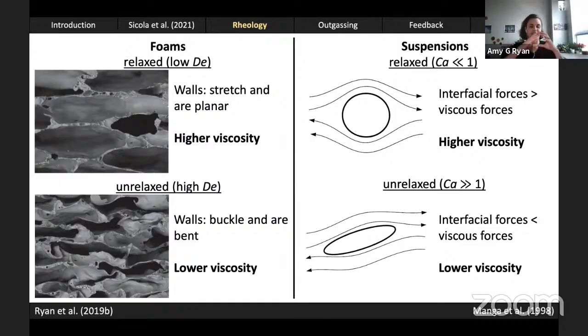In contrast, if that bubble is unrelaxed, if it's been deformed, the melt doesn't have to go as far to deflect around it, and the overall suspension viscosity is a little bit lower. So I would argue that though they're fundamentally different materials, foams and suspensions can be understood through the same sort of lens, thinking about the relaxation state of the materials present.